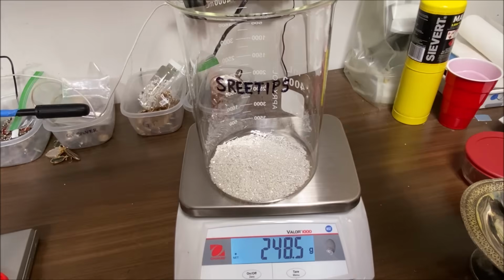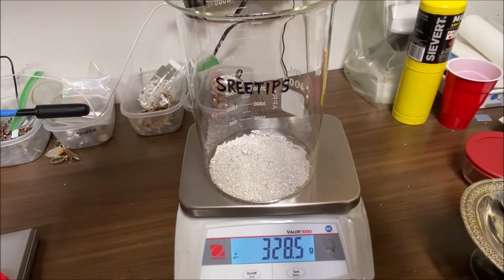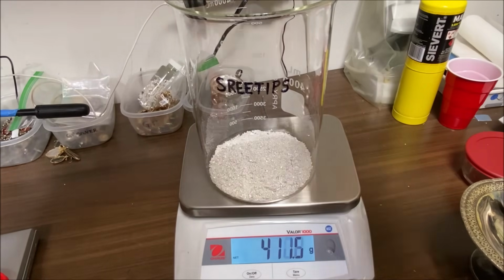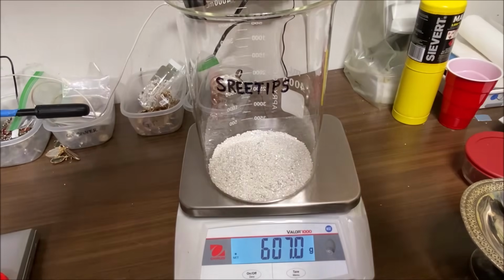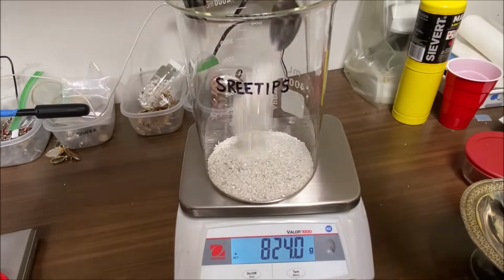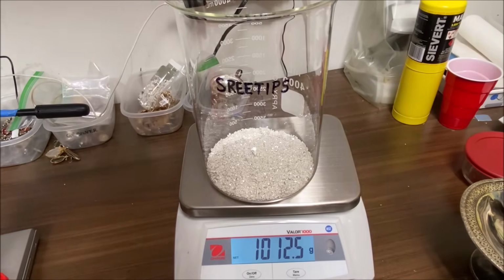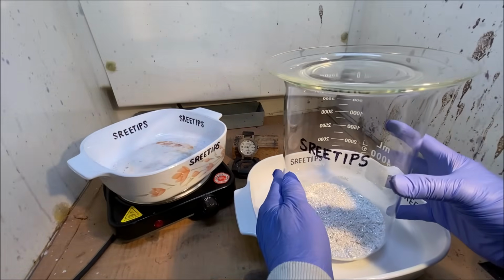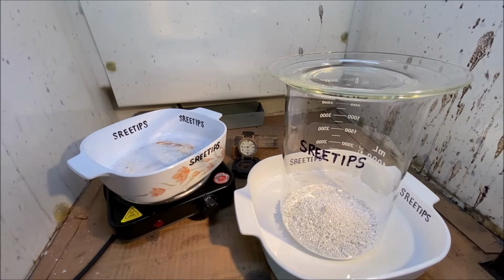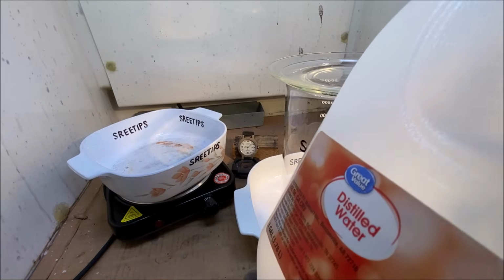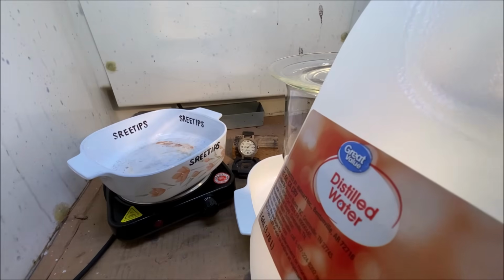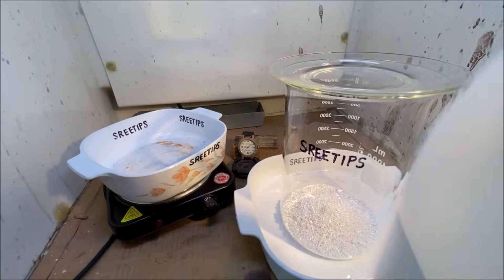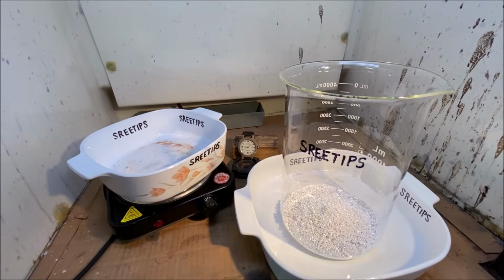for the beast. 1 kilo of pure silver crystal. There we go. We got 1,012.5 grams of high purity silver in a 4-liter beaker. Here's our 1 kilo of pure silver crystal. And to it, I'm adding about 1.5 liters of distilled water. This is for the electrolyte.